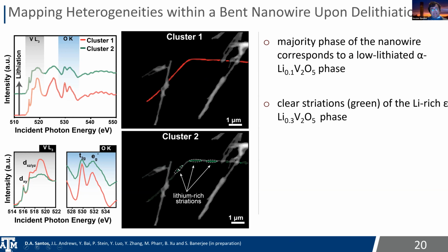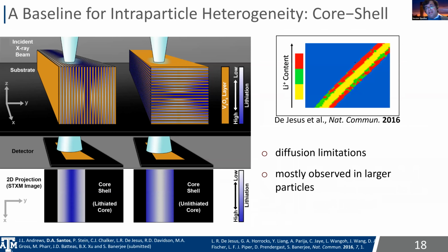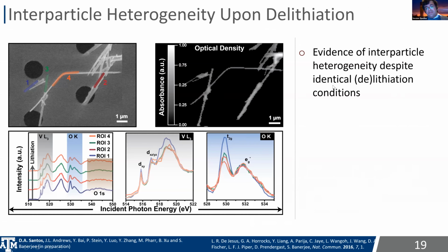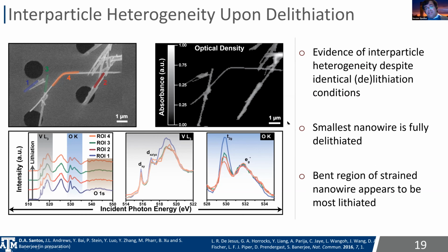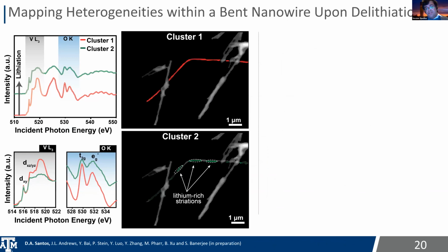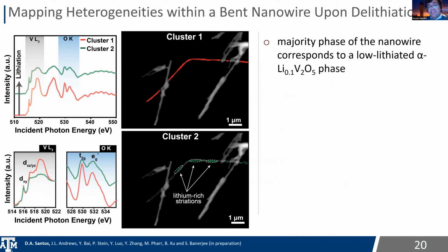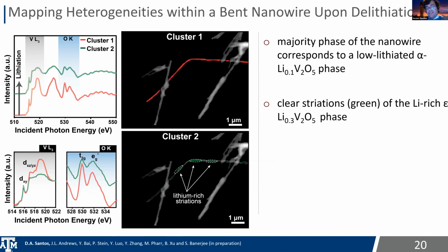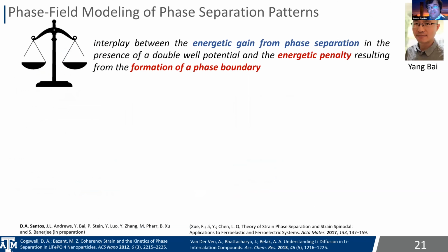Especially during lithiation, the domains that we see, and I showed you an example of this here, tend to be somewhat random, not entirely random. The specific morphology is determined by these nucleation restrictions along the wire, which could be affected by local topology or the presence of local defects. Whereas during delithiation, we actually start to see something that looks like what you would expect from thermodynamics, from spinodal decomposition. So we can start to see these lithium-rich striations, and the majority phase corresponds to low-lithiated alpha, whereas then you've got these striations of this epsilon lithium V2O5 phase.